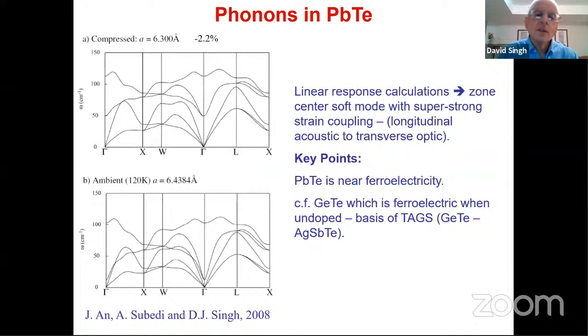All right. So the next question is about the thermal conductivity. And so the thermal conductivity in materials like this is controlled by the lattice. In other words, the atoms vibrate, and there are phonons, or lattice vibrations, and these lattice vibrations carry heat. And so understanding the lattice vibrations is what's important to understand the thermal conductivity. And so I wanted to understand more about the thermal conductivity of lead telluride. And so you can calculate the phonons of lead telluride. So this is the plot, similar to the band structure plot. It's in momentum space of the shape of the phonons down here.